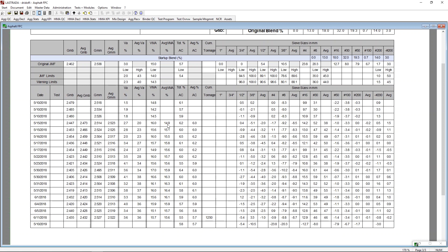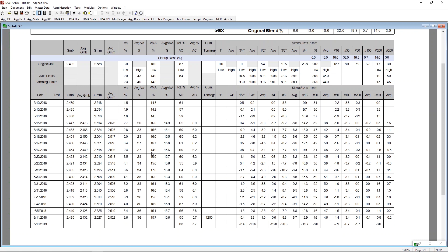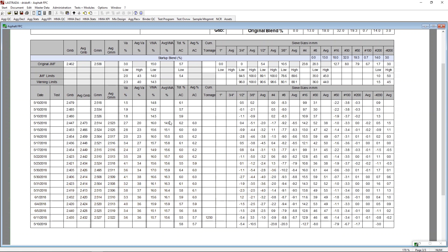What we kind of see here in the VMA data is we see a trending from just under 15 all the way up to 17, and then we start to trend back down roughly. And to show that trend, I went ahead and added a column where I'm actually showing the running average of 4, which helps smooth out some of the data. So you can see that we've been under 15. We trend up, we trend up, we trend up to 16, 16.4, and then we start to make our way down.